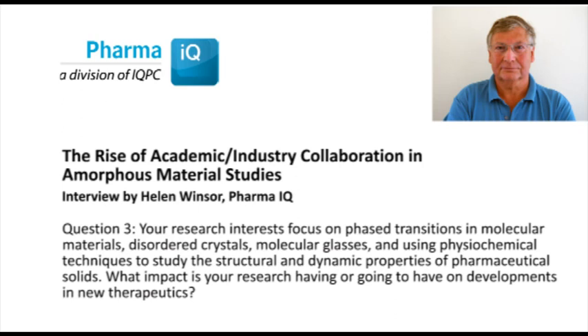Yes. For example, I can cite a few. Our research allows us to identify the factors which control the propensity to amorphize upon milling and dehydration, for example. It allows us to predict the value of the glass transition temperature, which is an important factor to predict the stability of the amorphous compound. Also, in terms of prediction of the phase diagram of polymer excipient mixtures, to localize the favorable zones in concentration and temperature, and this needs to associate experiments and modelization. And we could provide some recipes in this domain.